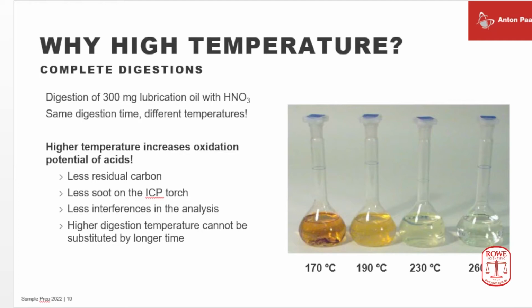Take the same thing to 230 degrees, slightly yellowish coloration. That's a solution that I would dare to use on an ICP. Still some residual carbon in there, but the ICP will burn that anyhow. The ideal way, you see here, a digestion at 260 degrees, a water-clear solution. This is what we call a complete mineralization of the sample, and this is the ideal condition for trouble-free analysis